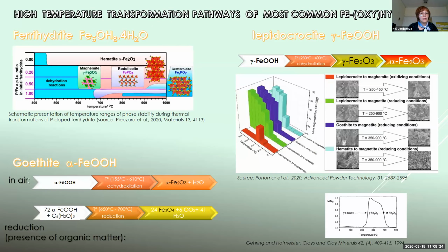So I will now shortly mention the high temperature pathways of transformation of different iron oxyhydroxides, because these reactions play important role in understanding the magnetic properties which we measure in materials from archaeological sites. It's well known that most iron hydroxides transform to a final product hematite during heating. But in the presence of organic matter, which creates reducing conditions, the pathway can go through intermediate formation of strongly magnetic phase maghemite, which further transforms again to hematite. And there are many studies demonstrating these transformation pathways.